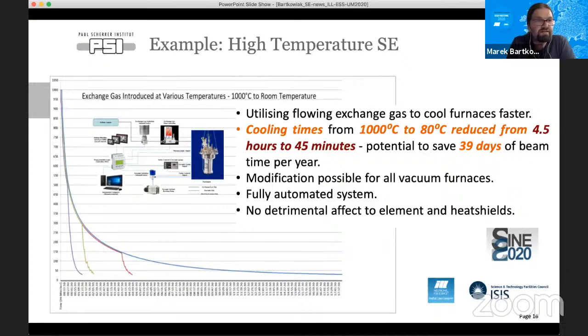What is shown here is an optimization process of a high temperature furnace, and the cool down of a high temperature furnace is fast cool down. What you can see in the graph here are different cool down curves, either with just leaving the system alone without heating, or by introducing exchange gas into the vacuum chamber at specific times and in specific ways. And by doing this optimization process, the cool down times from 1000 degrees Celsius to 80 degrees Celsius could be reduced from 4.5 hours to 45 minutes. So this is a substantial saving in beam time.